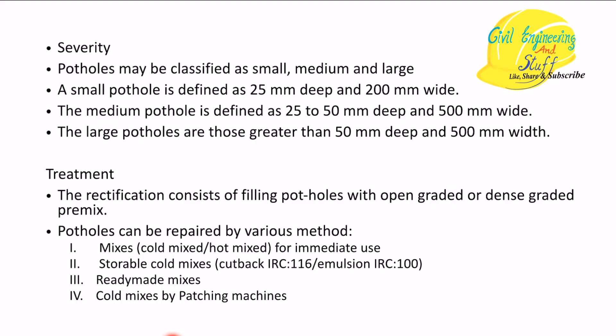Potholes may be classified as small, medium, and large. A small pothole is 25 mm deep and 200 mm wide. A medium pothole is 25 to 50 mm deep and 500 mm wide. A large pothole is greater than 50 mm deep and 500 mm wide. Treatment consists of filling potholes with open-graded or dense-graded mix, repaired by hot or cold mixes, or using cutback bitumen or emulsions. Ready-made mix or cold patching mix can also be used.